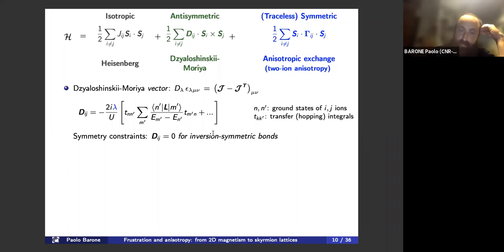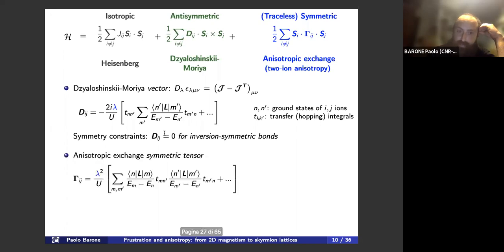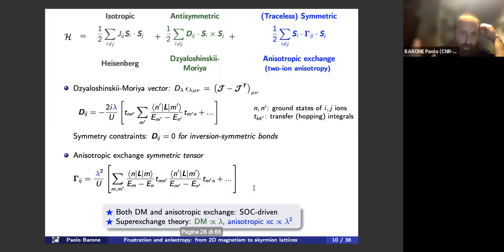perform a similar perturbative expansion. And finally, we also have this anisotropic exchange tensor. You see that it's very similar to the expression of the Dzyaloshinskii-Moriya vector. The only thing is that here we have an additional virtual intermediate state where we allow the atomic spin-orbit coupling to mix states on both sides of the system. So we can conclude that both the Dzyaloshinskii-Moriya and the anisotropic exchange are driven by the atomic spin-orbit coupling. And the reason why this anisotropic exchange is usually neglected is because it scales as the atomic spin-orbit coupling constant squared.